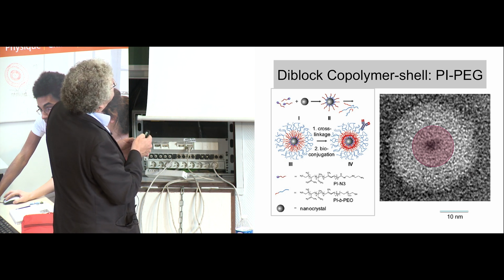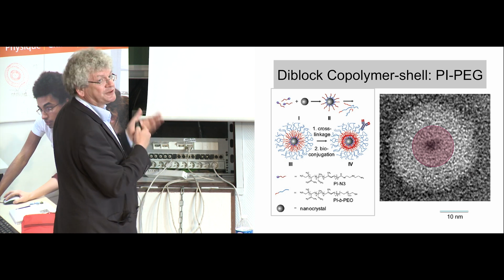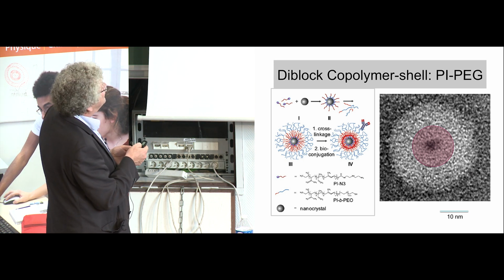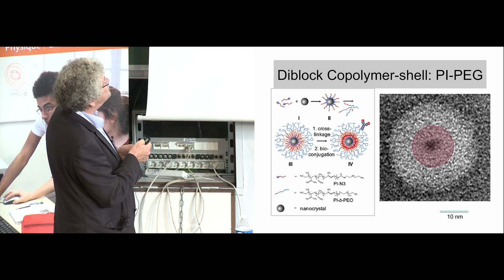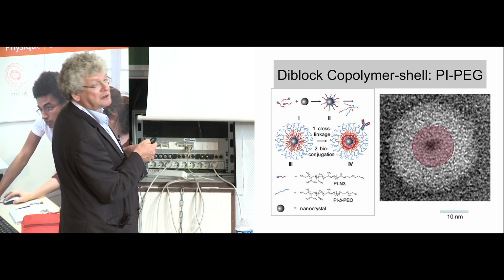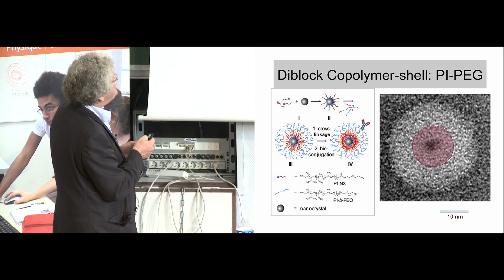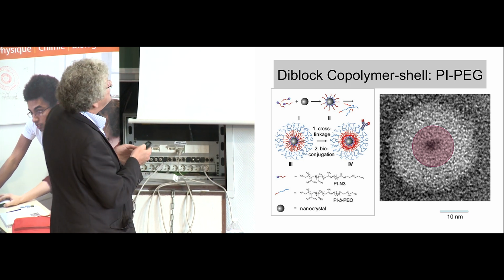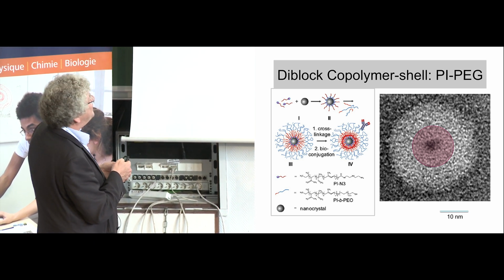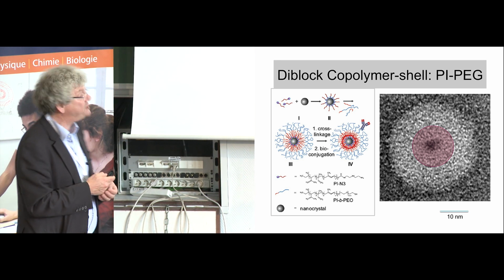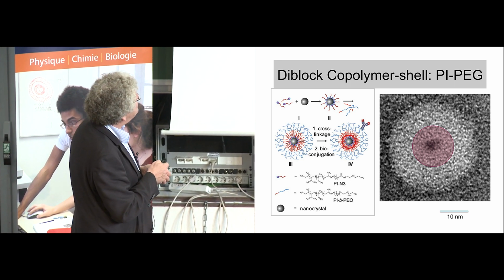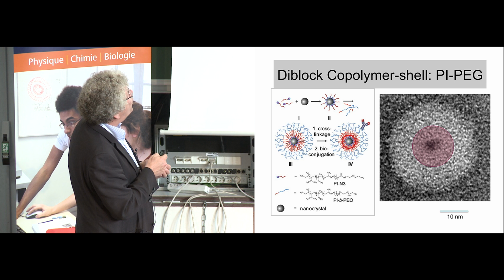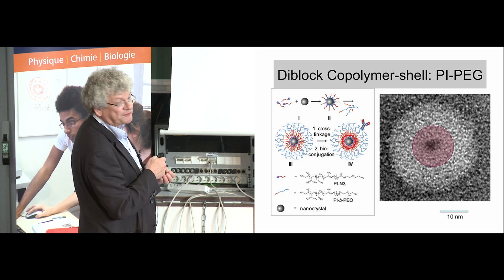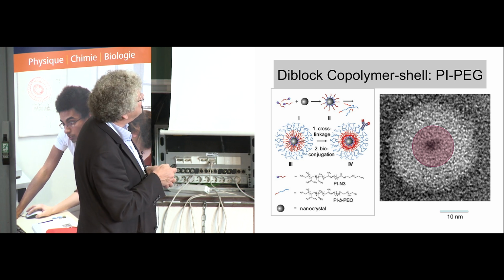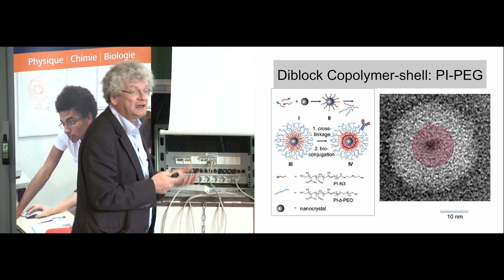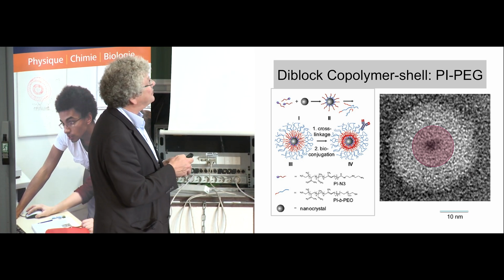So this is ligand exchanged, still in THF. And then we add a diblock copolymer consisting also of polyisoprene and PEG, polyethylene glycol. And then if you transfer this to water, then immediately a micelle formation occurs, self-organization, of course, and encapsulates these particles which work as a seed for this micelle formation. And then you can cross-link the polyisoprene part radically, and this gives then a very stable shell.